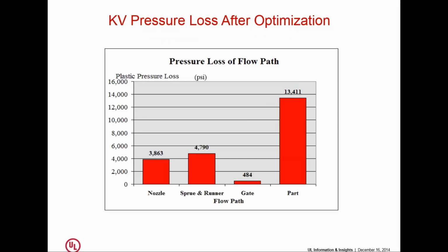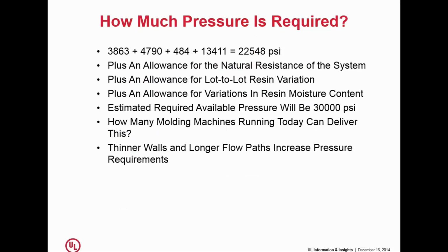So then the question is, how much pressure would you have to have in order to effectively and repeatably make this part? Well, if you add the numbers together, you get this value, 22,548, and people would say, well, if my machine can generate 23,000 psi, then I'll be fine. But there are some things that go on top of this 22,500 psi, not the least of which is the natural resistance of the system. Whether you have a hydraulic machine or an electric machine, there's a certain amount of inertia required just to push the hardware, the screw.